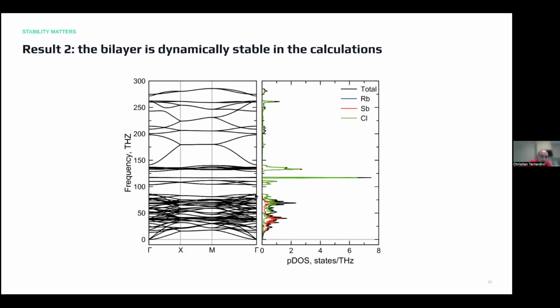And specifically, first of all, on the phonon calculation, we look to see if there are any negative optical branches. You see here the acoustic branches, which are usually three. Most of the time they are 0 at gamma and then increase. All the others are the optical branches that describe the perturbation between the atoms inside the crystal. The acoustic branches describe the perturbation of the lattice. What we have seen is that when there are no negative optical branches, like in this case, we can say that the structure is stable. So actually it's dynamically stable.